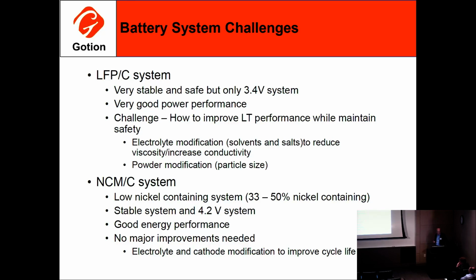The challenge here from a cell perspective is really low temperature performance. LFP itself is not a very conductive material, and it's quite bad at low temperature. We're working on this because it's an automotive demand, minus 30, minus 40 degrees, depending on the region you're in. Obviously, in the colder regions it's more of a challenge. We're working on that by changing the viscosity and increasing conductivity at low temperatures.